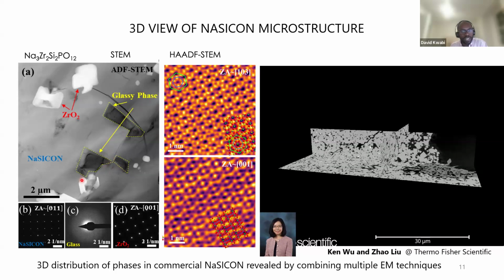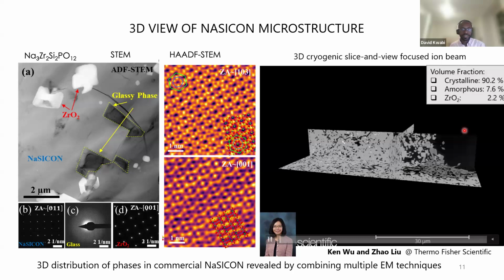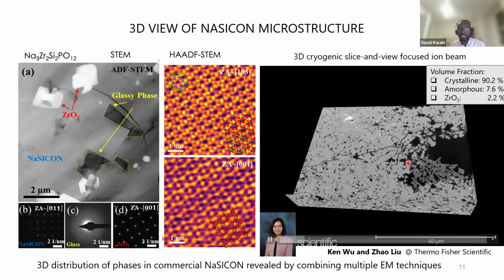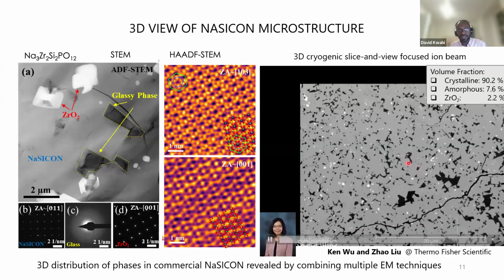So my collaborator Miaofang used high-resolution electron microscopy to map out the crystal structure of both the NaSICON and the zirconium oxide crystalline phases. And then she used what's called a 3D cryogenic slice and view focused ion beam technique, where essentially they mill out very thin sections of material and image that material with electron microscopy. She used that technique to reconstruct a 3D picture of how the various phases are oriented.